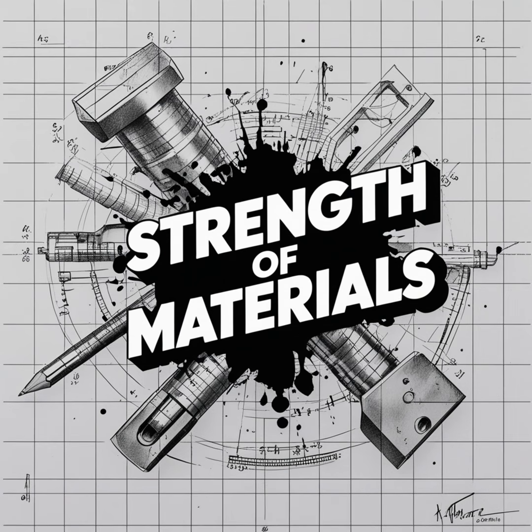That's a perfect visualization. You fire these tiny spheres at high velocity. Each piece of shot striking the surface acts like a microscopic high-speed peening hammer. When it impacts the metal, it imparts a tiny, shallow indentation or dimple into the surface. And what does that microscopic dimple do to the metal underneath? When the shot hits, it stretches the top layer of the metal plastically. It yields the metal right at the point of impact, forcing it to spread outwards, like dropping a bowling ball in mud. Okay. But the thick bulk of the material underneath hasn't been hit. It hasn't yielded. It is still perfectly elastic. So the bulk underlying material acts like a giant spring, trying to push that stretched, dimpled surface layer back to its original size. So the top layer wants to be bigger. The bottom layer is forcing it to stay small.